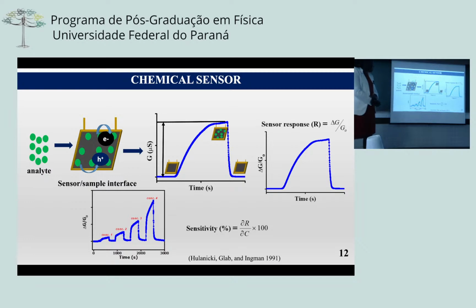So if you have an analyte, and this is your sensor and sample interface, you expose your analyte to the sensor, which is coated with a sample. Then you can have interactions taking place, adsorption, or electron donation or electron acceptance, which leads to a change in the conductance. So this is a sensor without exposure to analyte, with exposure to analyte, and after desorption takes place. From this, you get the sensor response, which is the change in the conductance over the base conductance. If you do this over a range of concentrations, you get a slope that gives you the sensitivity.